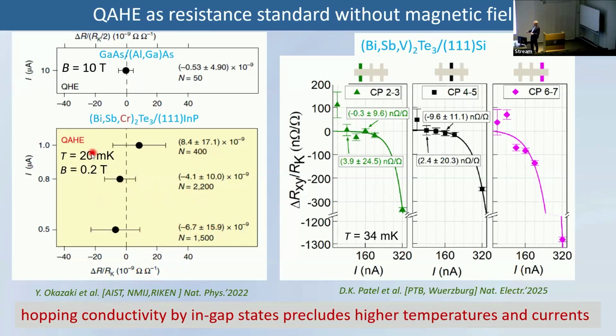You have to be at a much lower temperature. You are in a small magnetic field just to get rid of domains, but it's kind of unimportant. But you see that the accuracy is maybe one order or two orders of magnitude lower, but still it is impressive. You have accuracy of the order of 10 to the minus 8. Yeah? So this is very impressive. We expect progress to make this very precise. The only problem is this very low temperature.